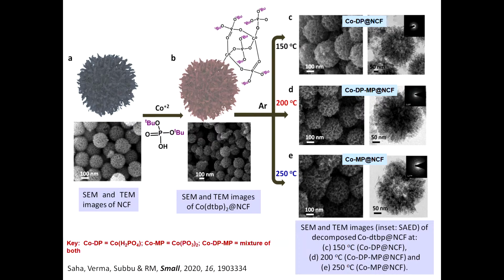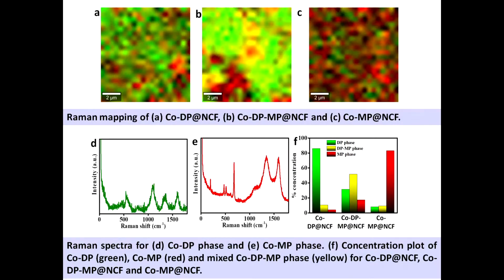And what is important is my collaboration with Subbu, who is also a Raman expert, so he went on to do Raman imaging. So this would be the Raman spectrum of the pure dihydrogen phosphate, the DP phase, and this will be the Raman spectrum of the metaphosphate phase. So when you do a Raman mapping or Raman imaging, whatever you call it, you can see predominantly green at 150 and predominantly red at 250, and at 200 the regions of green and red merged together.